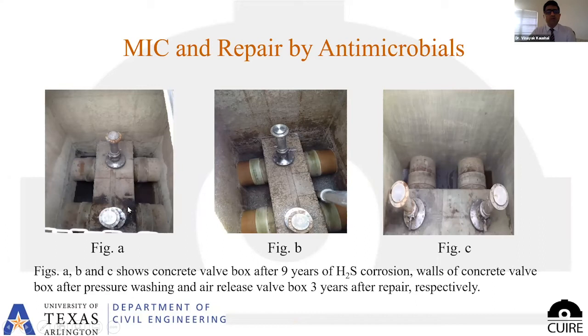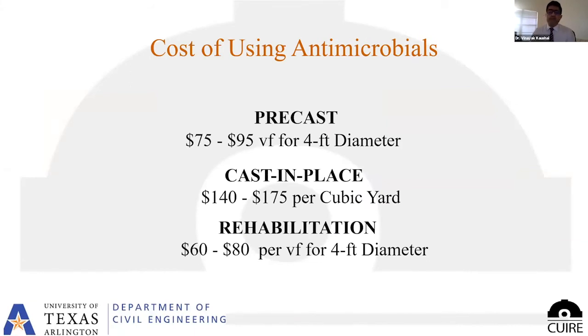Now, as you can see in this slide, we have a concrete valve box which was affected by MIC, as you can see here, this corrosion on the concrete surface. And as a result, this antimicrobial was used. The good thing is that it could also be used on treating the walls of the hydraulic structures, so you don't have to rebuild those, in the form of a coating, right? And also, of course, in the very beginning. So now you can see figure C, which shows how the antimicrobial mix was treated, and as a result there is a significant decrease, or at least no corrosion which can be seen, and we can get rid of this issue. Now the thing which comes into play is the cost.